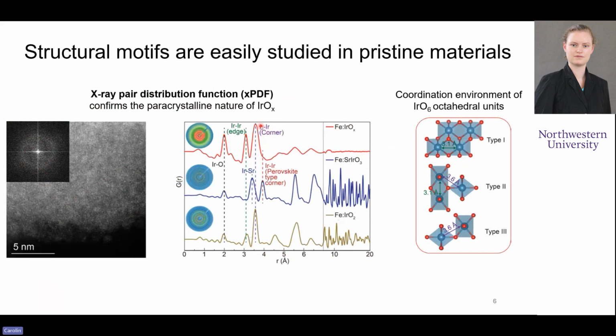And so from the different kinds of motifs that we find in these patterns, together with X-ray absorption and XAFS data, we can deduce what kind of structural motifs are present in these materials. So in an iridium oxide, the base motif is always this IrO6 octahedral unit. And we find different kinds of bond distances present. We find the iridium-iridium distance for edge-sharing octahedra at 3.1 angstroms. And we find the iridium-iridium distance for corner-sharing octahedra at 3.6 angstroms. And so we have 3 types of structural motifs that are present.